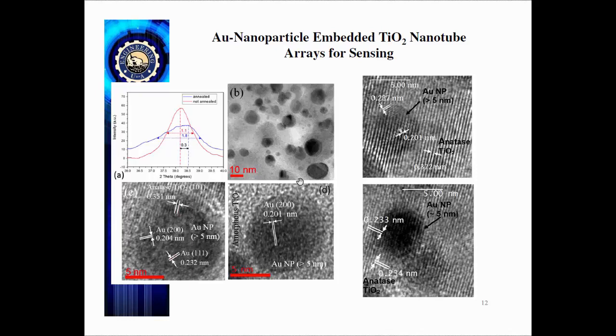Because for the plasmon resonance to be really effective in SERS, there's the electromagnetic component, which is not the whole story. There's also a chemical component that's known as interface chemical damping, or Landau damping. And that in the gold nanoparticles is very important, related to factors such as the yield of hot electron injection. Okay? So when you have a heteroepitaxial interface, that dramatically enhances the possibility of direct injection of hot electrons from the gold to TiO2, which can then really improve your signals.